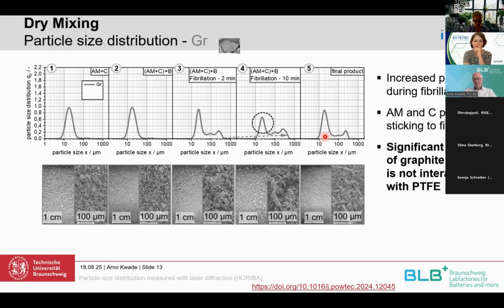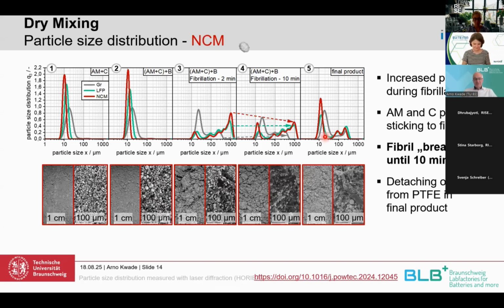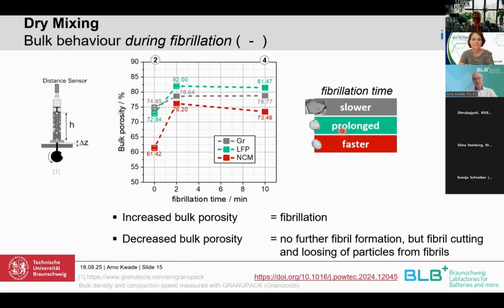So it's not such a big interaction of the graphite particles with the PTFE. It looks a little bit different, or somewhat different, if you look at the cathode materials. You see here that we have much coarser and many more granules, especially at the beginning of the fibrillation process. So there's a decrease with increasing fibrillation in fibril size and length. And after homogenization, we also have a decrease in the granulation size and granulation amount.